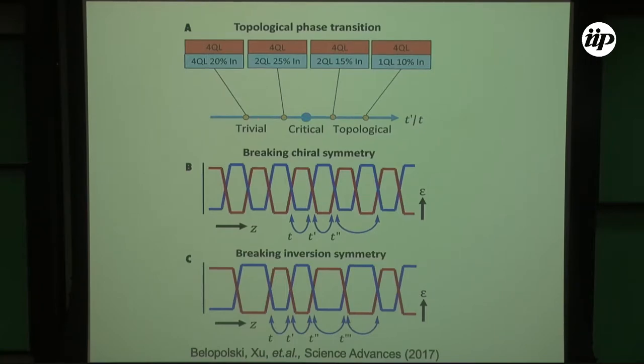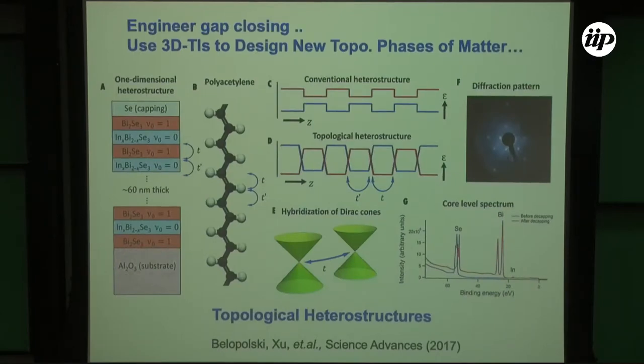One way to understand that, let me go back and try to give you an intuitive feeling, is that, let's say T double prime is small, in other words, this blue layer is thick. In that limit, we just have a stack of isolated topological insulator layers. So globally, there are no topological states. I just stacked some layers, right? But what if this T prime is large, so that the Dirac fermions hop, and then there is a three-dimensional global state. So what is the critical value of T prime where that phase transition happens? When T prime is large, you enter a topological state, but if T prime is small, then the bismuth selenide layers are isolated, and there's no propagation in this z direction, so you are in a trivial state.